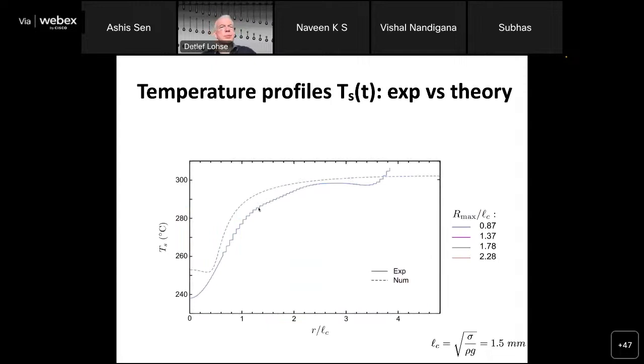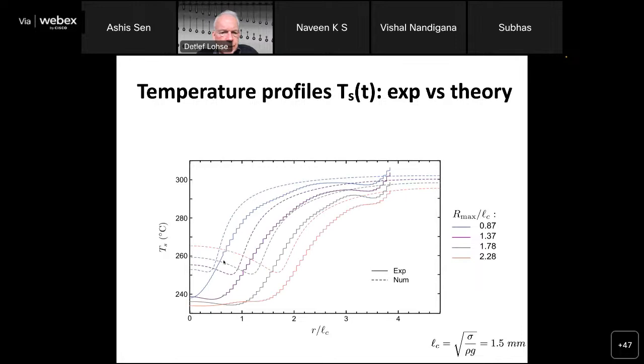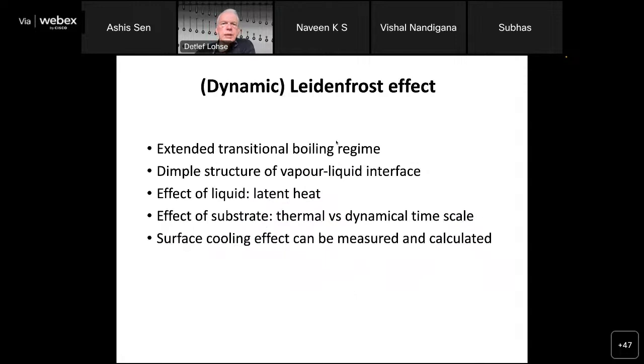And when we now compare the curves here, the solid curve experiment and the dashed curve is numerics, now for different droplet sizes, and it's not bad. So, I mean, you see this cooling down right here, and this is also in the other curves here. So in the numerics, we clearly see the dimple here in the middle. In the experiment sometimes, but there is some wiggling, so the dimple in the middle is a little bit washed out in the experiments. But I'm particularly glad that this cooling down effect can be calculated.